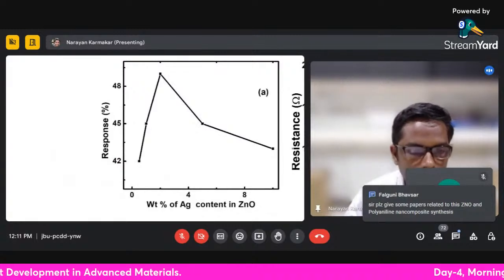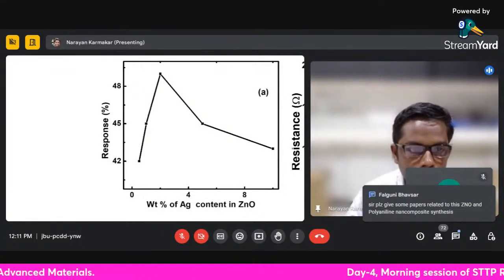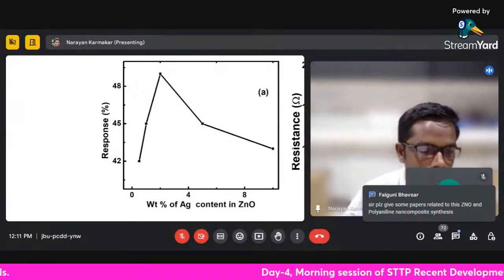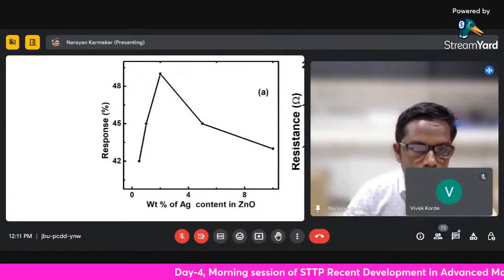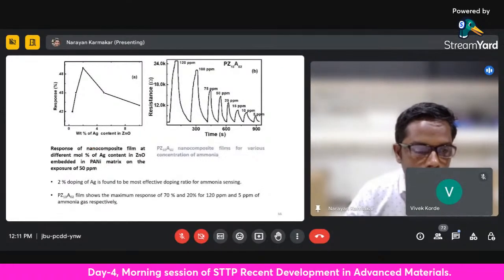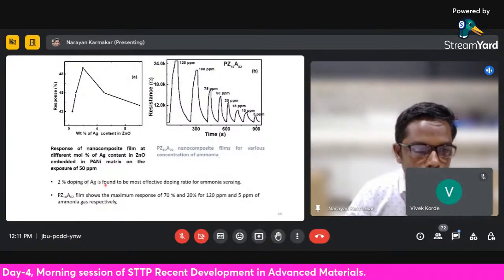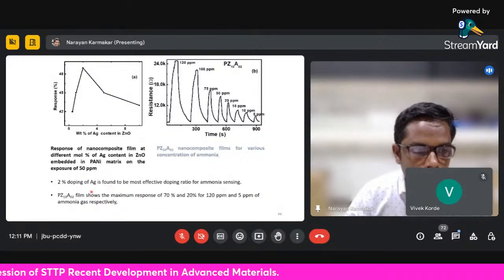After that, what we did is we doped with silver and studied the variations, and we saw that it shows a good response at over 2%. So 2% doping is found to be the most effective doping ratio for the ammonia response.